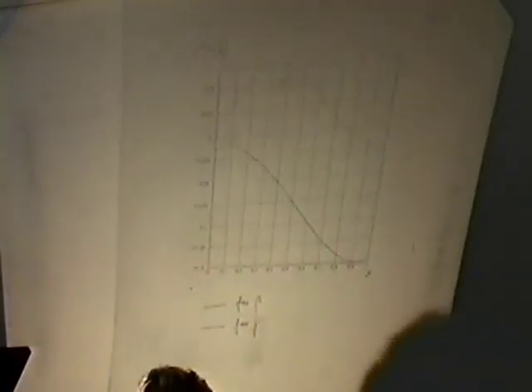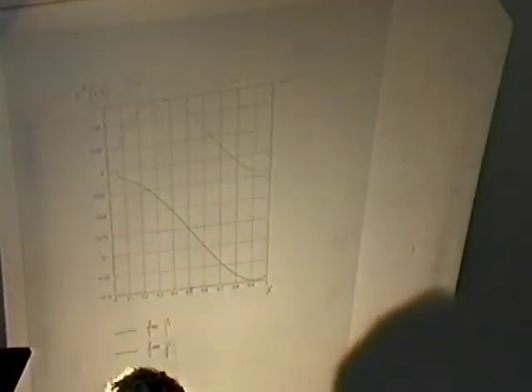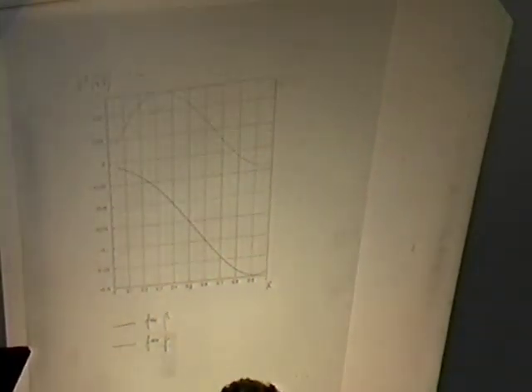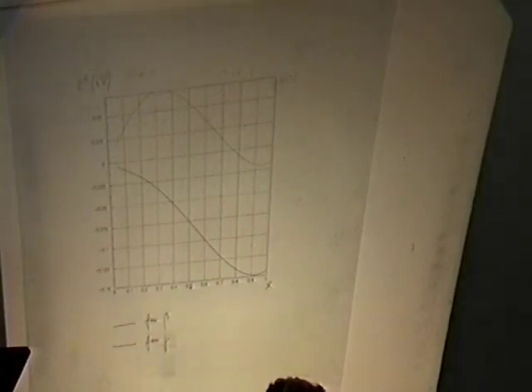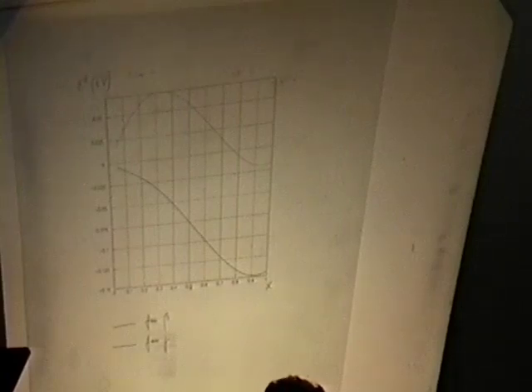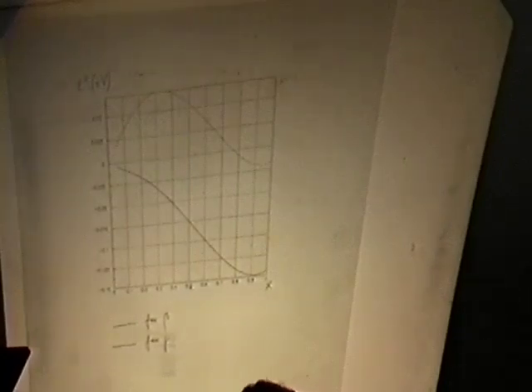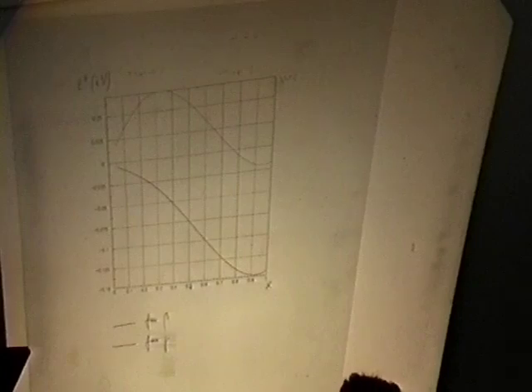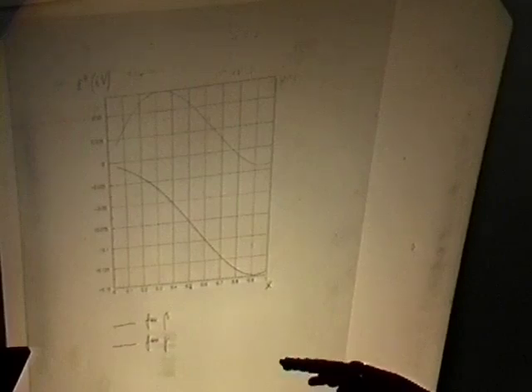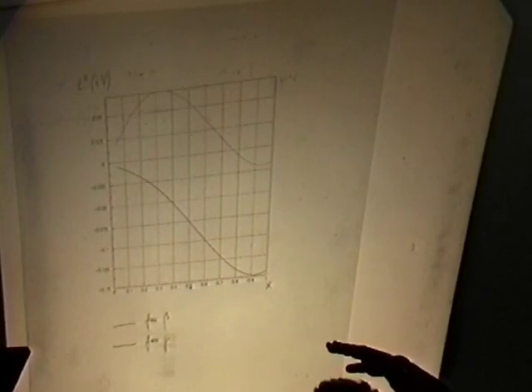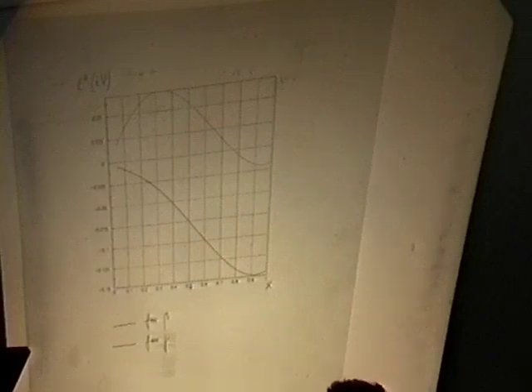Another observation is the calculation of the energy of the hydrogen nuclei in this phase. You can see the solid line shows, as usual, the beta phase, the dotted line, the gamma phase. And you can see that the energy of the hydrogens in the gamma phase is quite higher. What does that mean? That means that the formation of the beta phase is an exothermal reaction. The formation of the gamma phase is an endothermal reaction. That means that hydrogens, while in the beta phase, are located deeply in the well, while in the gamma phase they are located just in the upper part of the well. So they are less bound in the gamma phase than in the beta phase.